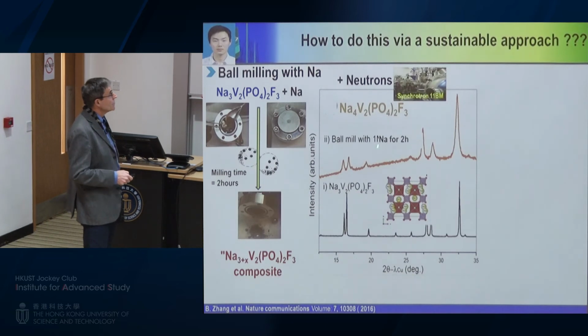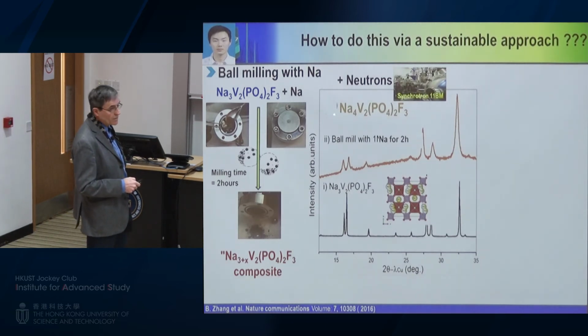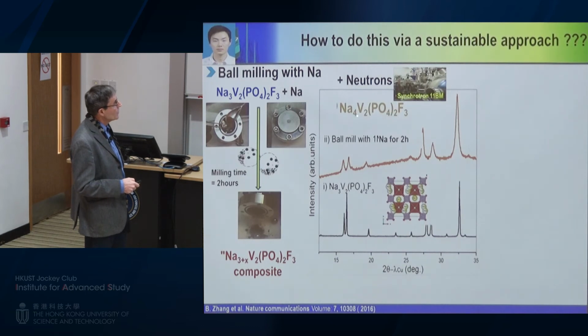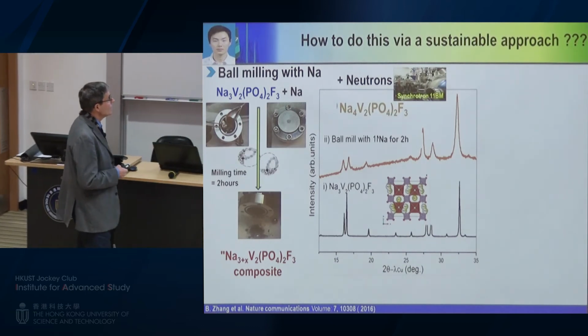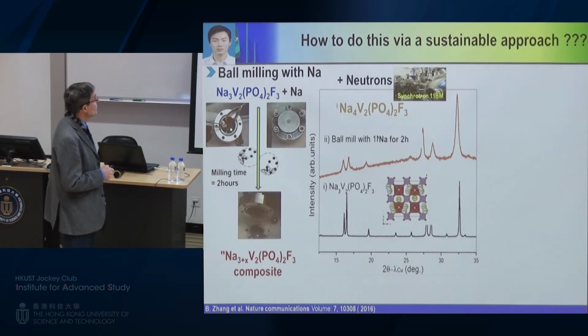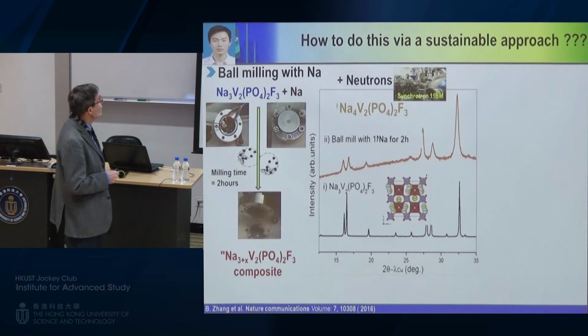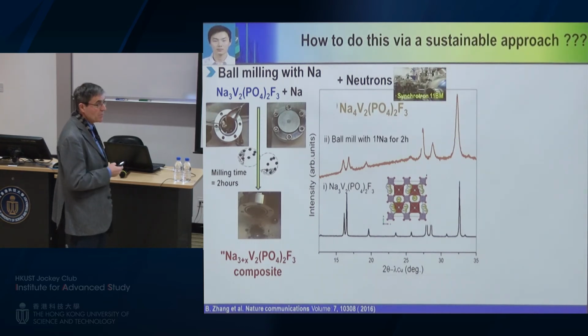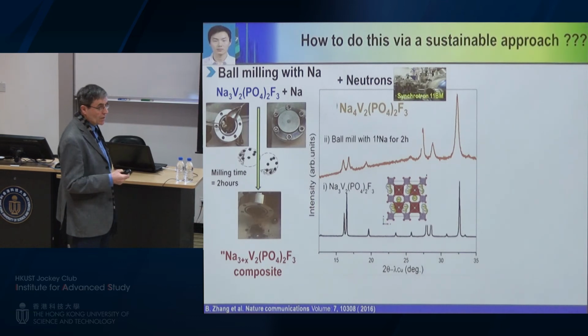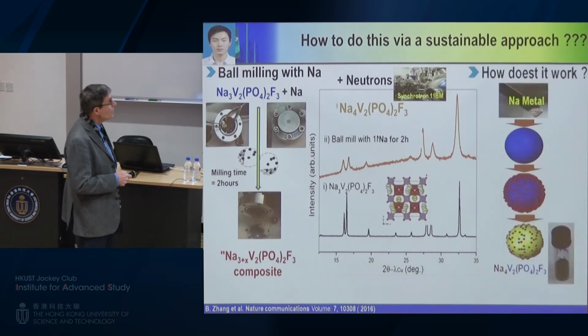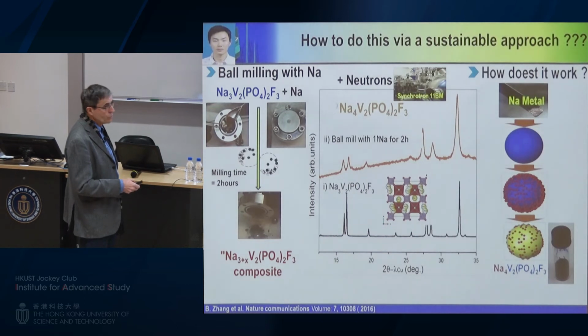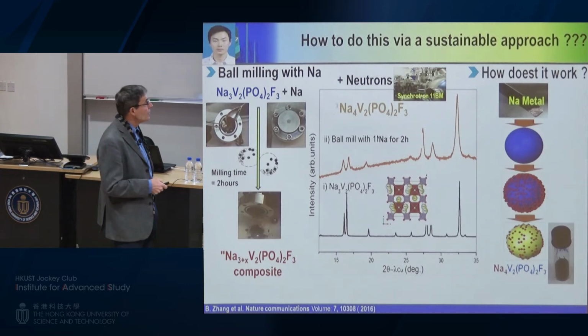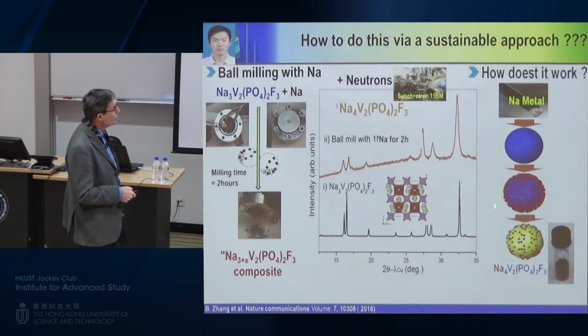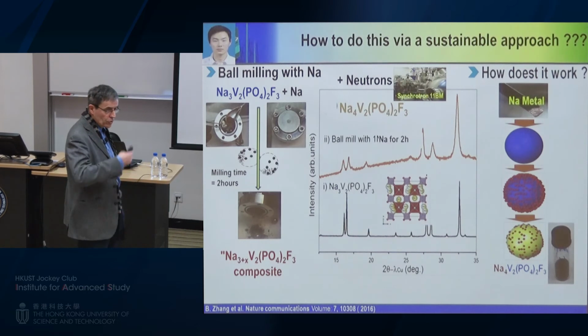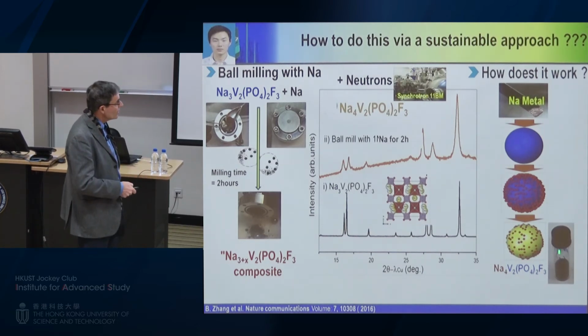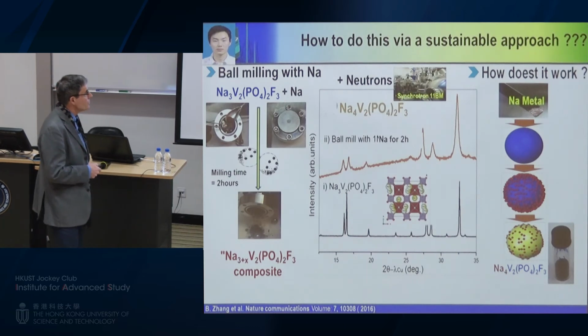We could, in this case, solve the structure, and this compound, again, was never reported before, and we are going to use this material as our positive electrode. What is interesting for people who have been working on this kind of reaction is that trying to ball mill something with sodium was not obvious at all. And surprisingly, this works. Why did it work? Because of the huge chemical reactivity of sodium with a powder. When you put sodium in contact with the powder, you form a shell, and then you continuously break this shell to get very highly divided particles.